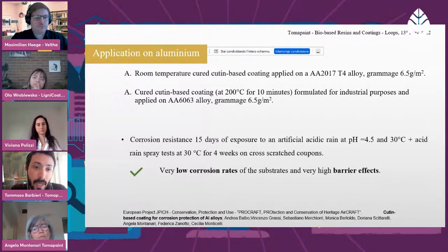And the same good results have been obtained for a cutin-based coating with similar grammage applied on AA6063 aluminum alloy sheet. And so both these tests demonstrate that cutin-based lacquer gives a high level of protection of metallic substrates.